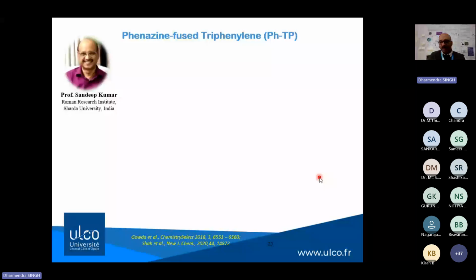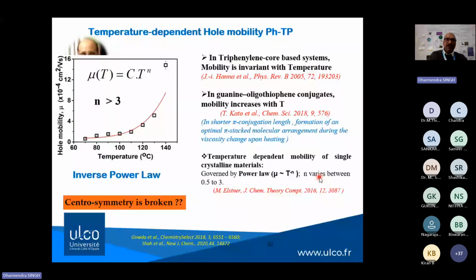But here we found very interesting results. Our hole mobility was on the order of 10 to the power minus 4 centimeter square per volt per second, and we observed temperature-dependent mobility in these compounds: the hole mobility was increasing with increasing temperature. As I told you before, in triphenylene-based systems the mobility was invariant with temperature. This was the established fact until 2005. Another group from Japan, led by Takashi Kato, showed temperature-dependent mobility in oligothiophene systems. However, their mobility was increasing almost linearly with temperature, and they said that viscosity is the factor for which this mobility is changing.